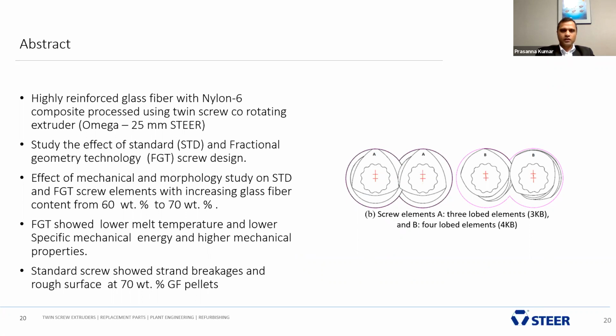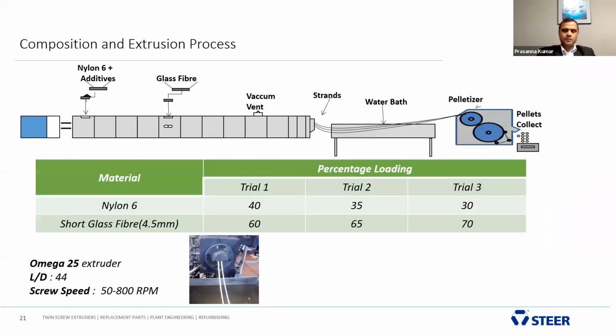We used an Omega 25 mm extruder, and the reason for us to do the trial was to compare the result between standard element geometry versus fractional geometry technology and see the mechanical results. The study was done using 60% and 70% glass fiber in nylon 6. The results we will share with you in the subsequent slides.